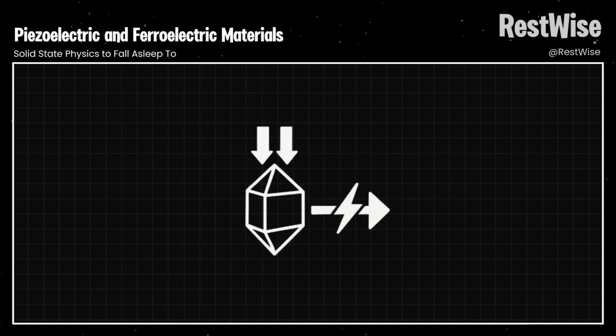That's the basic idea behind ferroelectric RAM, a type of non-volatile memory that keeps data even when the power is off. A typical ferroelectric material is barium titanate. In its high-temperature phase, it has a cubic structure and behaves like a regular dielectric. But as it cools below a certain Curie temperature, its structure distorts into a tetragonal shape, and spontaneous polarization kicks in. You end up with multiple domains, each having dipoles aligned in different directions.